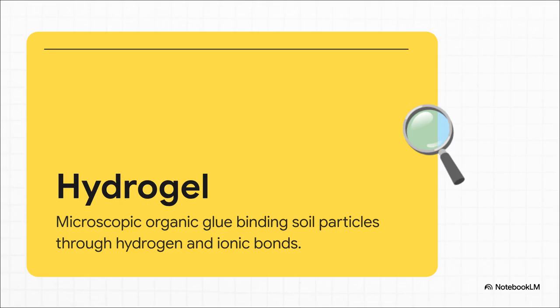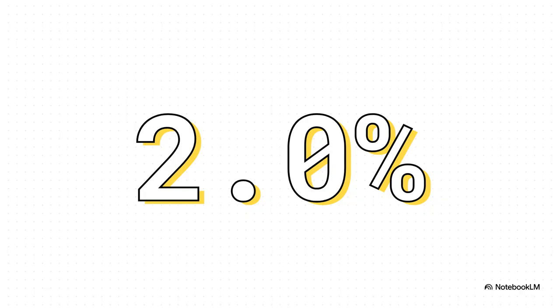Guar gum does this using hydrogen bonds, while xanthan gum packs an extra punch by adding stronger ionic bonds into the mix. So the absolutely crucial point to remember here is this specific number, 1.5 to 2.0%. The researchers found that adding just 1.5 to 2.0% of these biopolymers by dry mass achieves the exact same air-dried compressive strength as earthen materials stabilized with 8.0% cement. That is a massive wow factor. We are literally talking about replacing a highly pollutive industrial material with a tiny fraction of a biologically synthesized alternative and getting the exact same structural integrity.